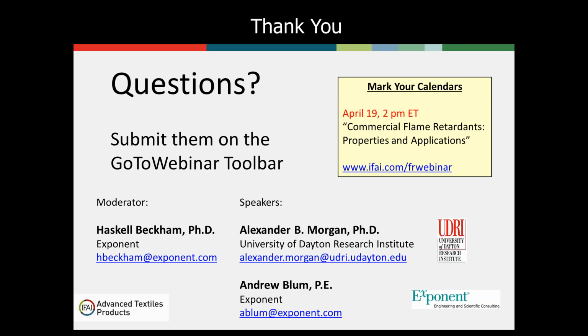And so there's a great deal of research out there for many different materials, wood, plastics, that have shown, running the cone calorimeter, you get a good data set: heat release rate, time to ignition, smoke production, and then you can take those results and correlate them up to the E84 test. And so that's the one that has been found to be the best one to correlate with, from my understanding. So Alex, I don't know if you've done any of that yourself. I have, with not quite as good success.